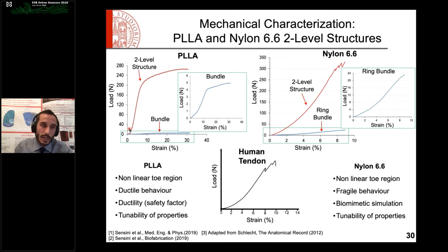You can see how all the structures show nonlinear two regions similar to that of tendon tissue, while the PLLA two-level structures show a ductile behavior similar to that of the bundles, whereas the nylon 6,6 showed an elastic brittle behavior very similar to the typical behavior of tendons and ligaments.